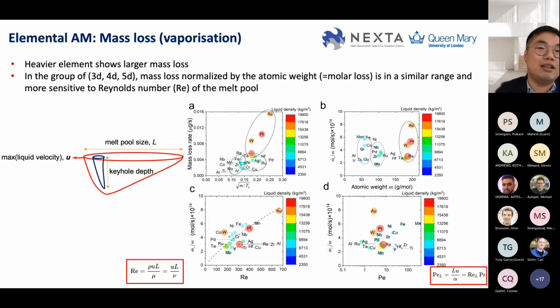diagram to understand the characteristic, especially the vaporization or mass loss. So it seems that the heavier elements show larger mass loss. In the group 3D, 4D, 5D, the mass loss normalized by the atomic weight is a similar range, but sensitive to the Reynolds number of the melt pool. The Reynolds number is defined here on the left-hand side: the maximum liquid velocity, and the melt pool length scale is taken as the characteristic length for the Reynolds number calculation here.